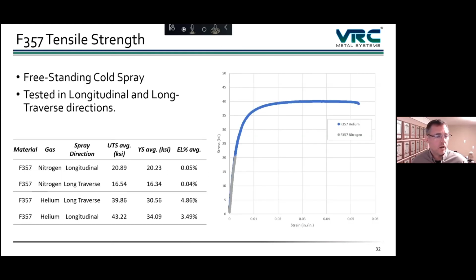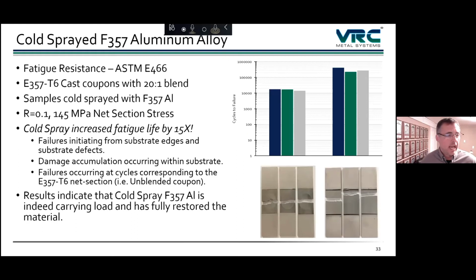This gives you a little more specifics about what you can get with helium and with nitrogen. Most of what I'm going to show you is helium, but we did also look at nitrogen. And when you nitrogen spray this same material, you do get a lower strength as well as a lower ductility. From a structural standpoint, certainly in this case, the preferred material would be the helium. Now, if you look at how this material performed in a conventional fatigue test, it's conventional from the standpoint that it's a load-controlled fatigue test.